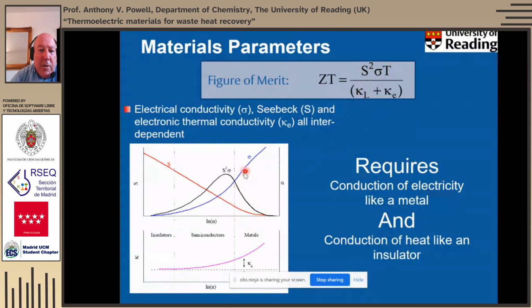So this S squared sigma term is known as the power factor, and that peaks somewhere in the middle here, which corresponds to heavily doped semiconductors. There's also, as I say, the thermal conductivity element of that, which is an issue, in that whilst the lattice part of the thermal conductivity is largely independent of the carrier concentration, the electronic part will of course get higher the higher the electrical conductivity, and in fact they are directly related to each other through something called the Wiedemann-Franz law.